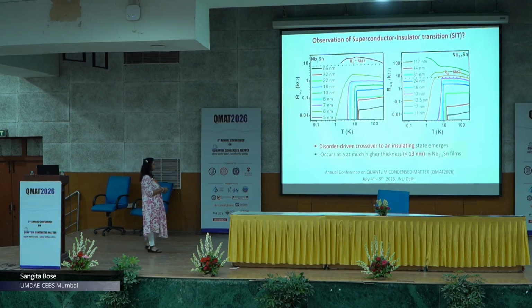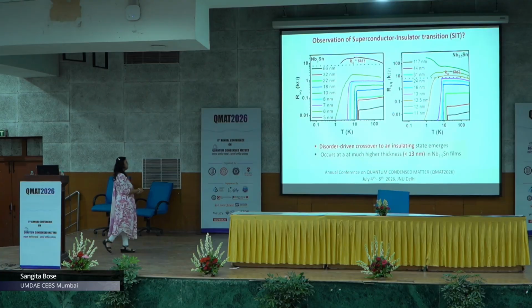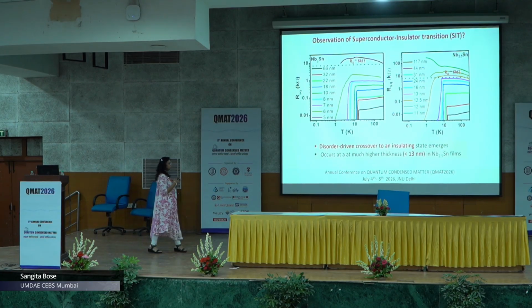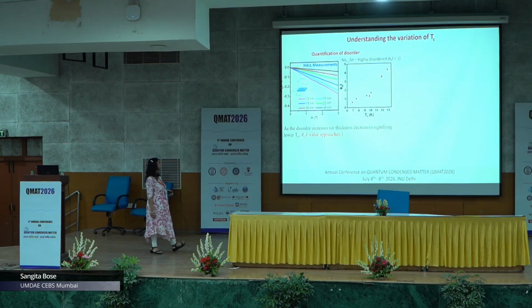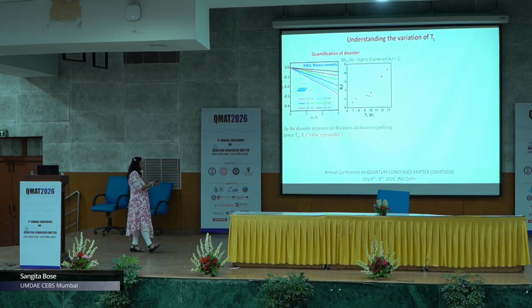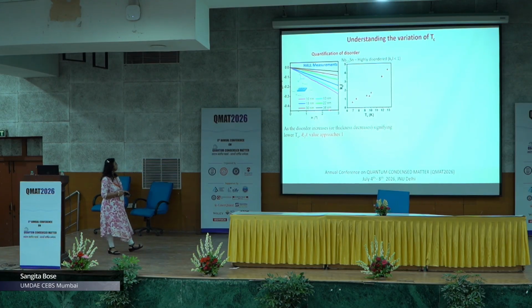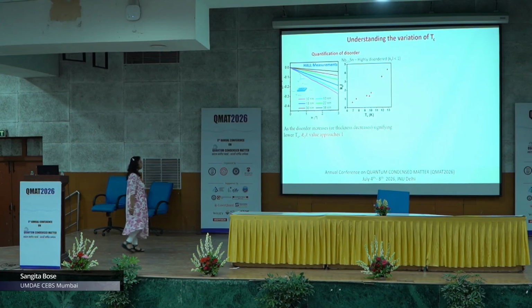However, for the niobium 2.5 tin system, what we noticed is that you see this superconductor to insulating phase transition, and this is happening at a much higher thickness of around 13 nanometers. So, below 13 nanometers itself, we start seeing superconductor to insulator transitions. Which tells you that the off stoichiometric film is of course more disordered, but we need to understand it or quantify it better to be able to corroborate our assumption. So, how do you measure the disorder in these films?